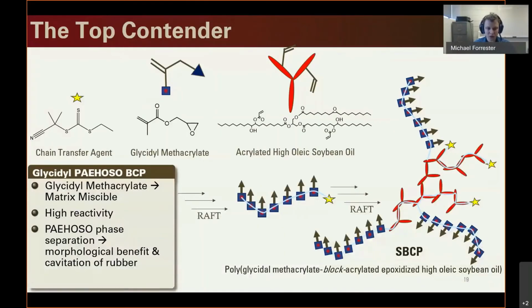So just to describe what this system is a little bit, one of the things that is unique about our group is that we're one of the first that have really been able to get high molecular weight thermoplastics out of soybean oil. And we've done that through utilization of the RAFT polymerization method. It's a controlled radical method that allows us to ideally control some of the gelation cross-linking events that can occur with these multifunctional molecules. So what we did is we created a glycidyl methacrylate block using this RAFT method. Once that was done polymerizing, we polymerized the acrylated epoxidized soybean oil. And that makes this kind of complex, branchy sort of block copolymer system.